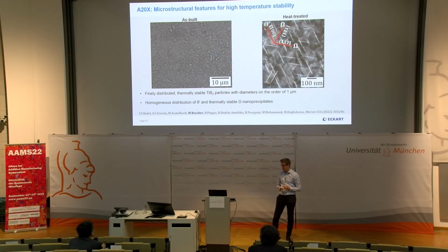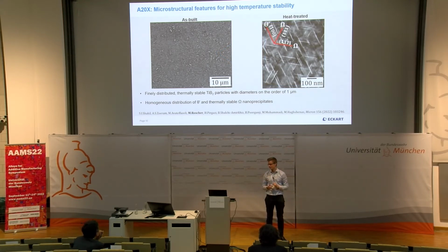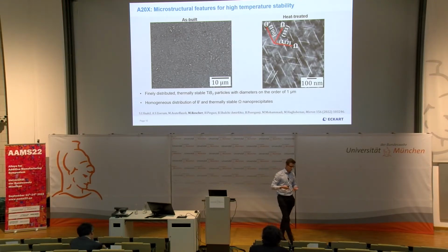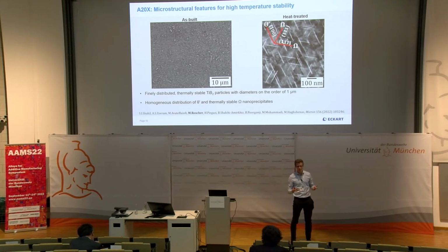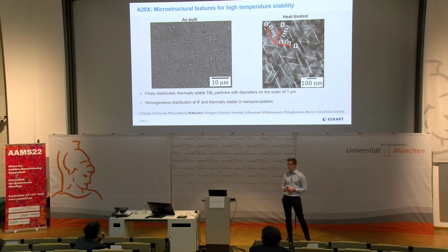However, there's a second factor, and this is related to the types of nanoprecipitates that form during heat treatment. As we can see in this TEM micrograph, there's quite a high volume fraction of plate-like nanoprecipitates present after heat treatment. We can identify two phases actually. One is theta prime, which is what you would find if you aged binary aluminium copper as well. It is simply part of this precipitation sequence when aging supersaturated copper-containing alpha solid solutions. There's a second phase, however, this is omega phase.